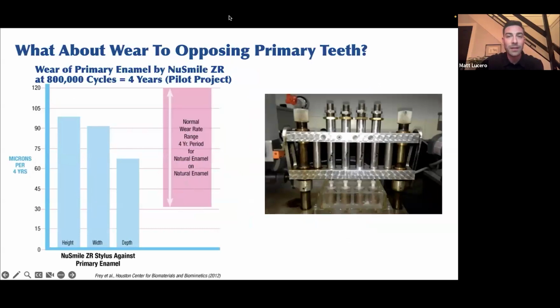And here's another one that shows wear to opposing dentition. You have a really strong material, so you would assume this is going to wear on the natural dentition, and it really doesn't. This is a study that was done with a Leinfelder machine, where they take these little zirconia pieces and put natural enamel under a bunch of cycles, kind of simulating 4 years of wear on a natural tooth. And you can see the wear that they found falls into the normal range of what we would expect to see either way.